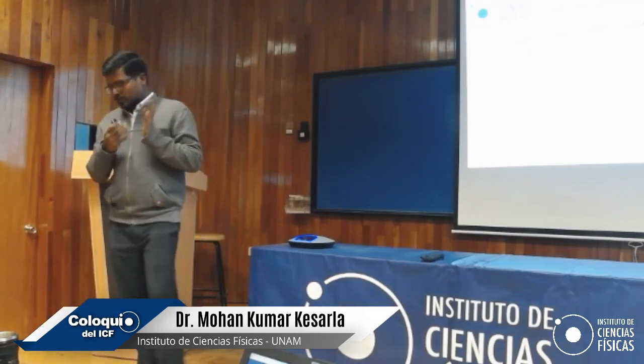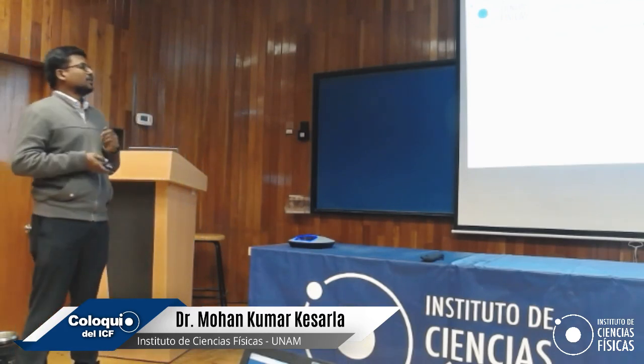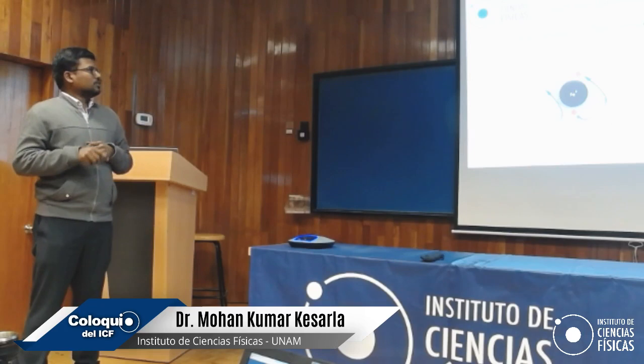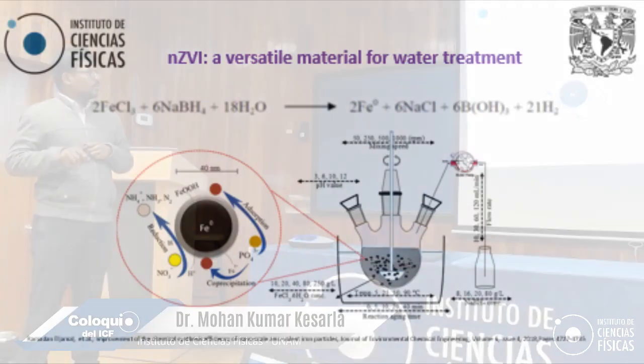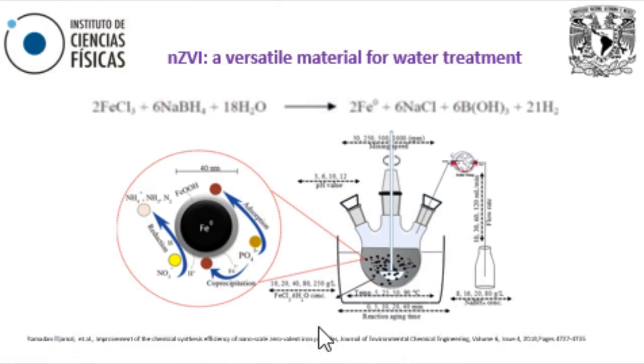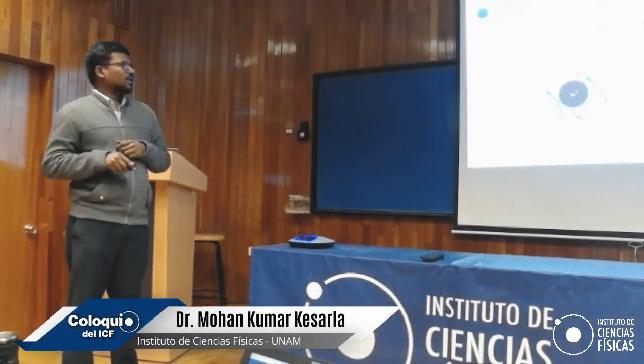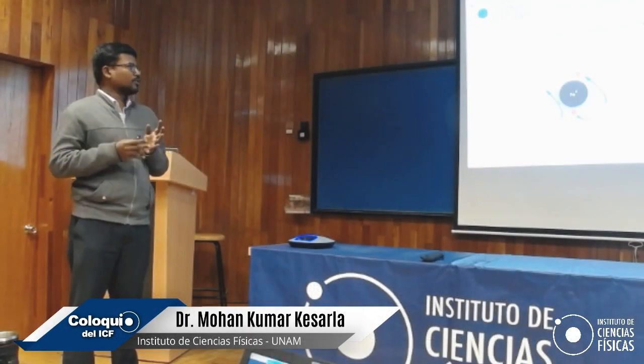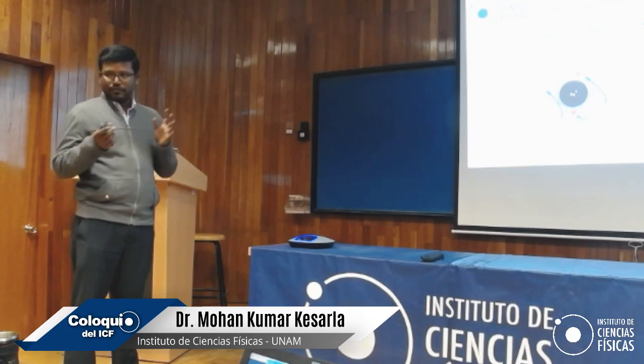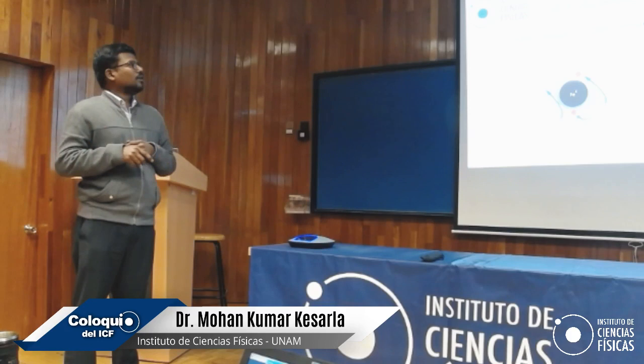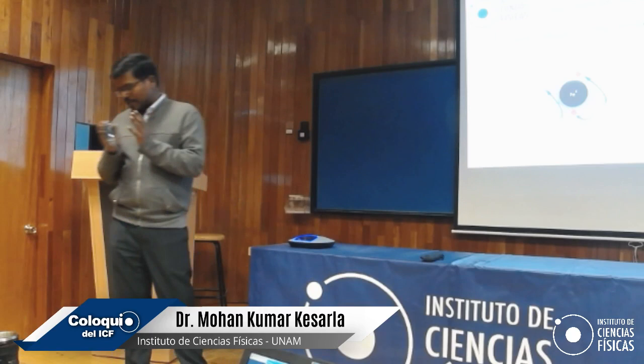But it has its own applications in water treatment. So how to produce this? Just take any salts of ferric chloride and supply it using a peristaltic pump, and supply sodium borohydride into it. There are many factors which influence the size and properties of zero valent iron. That includes the reaction time, temperature, the stoichiometric amounts of sodium borohydride and ferric chloride, the pH values, and the mixing speed. Since this is an exothermic reaction, it is highly recommended to do this reaction in a cold chamber.